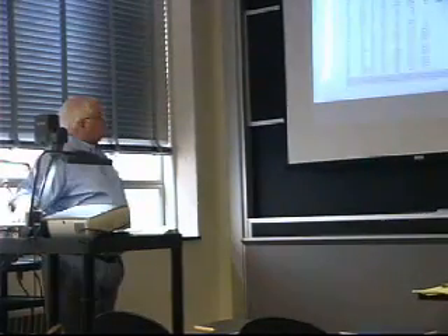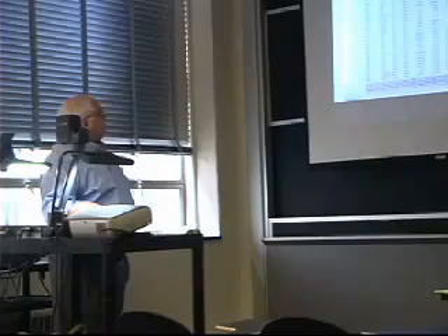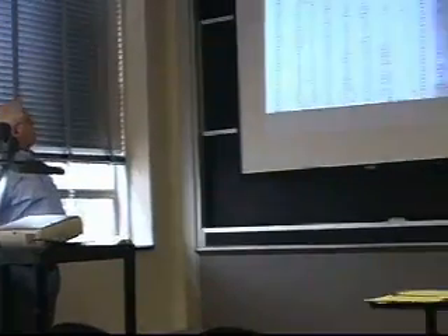There are lots of different aluminum alloys, just like there are lots of different steels. One of the things that characterizes different aluminum alloys is the amount of alloying element. So here's the alloy designation. The 1000 series means mostly pure aluminum, not too much other alloying element. If you look across here, these are all less than 1%. 3000 series is also fairly low, but a little bit higher. It's actually got a fair amount of manganese in it.